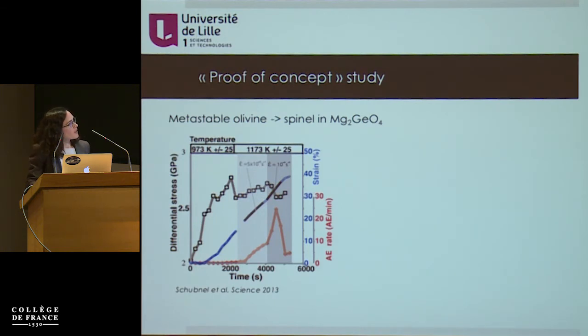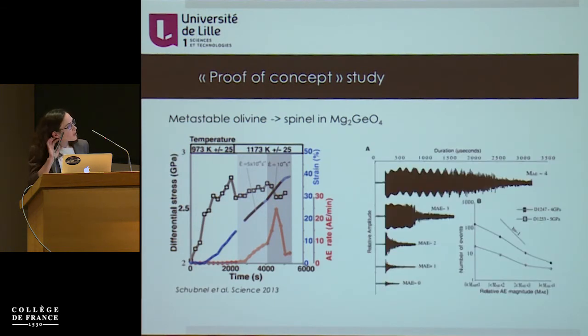And lastly, as I was telling you, we can do some unbiased statistics on the acoustic events, and this is what was done at this time. So magnitudes were really calculated for these different acoustic emissions. These two are saturated, actually, the system. And you can recalculate a number of events, classify them as a function of the magnitude, and the slope, actually, of this distribution is below -1. And basically, it means that this is close to a Gutenberg-Richter law.